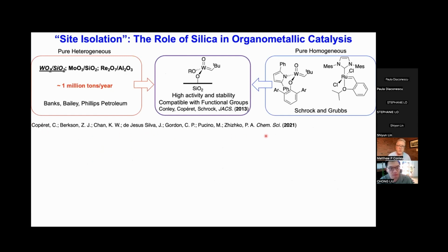So this is a recent review describing all of the things that have been learned from making well-defined heterogeneous olefin metathesis catalysts. And all of this work is inspired by the sort of pure oxide-derived systems, notably the tungsten oxide on silica catalyst, which is responsible for about 1 million tons per year in the ethenolysis of 2-butene to make propylene. I didn't dwell on this much on the first slide, but this is a reaction that's thermoneutral, but because of the complications with generating the active site in this material, you have to operate at very high temperatures.